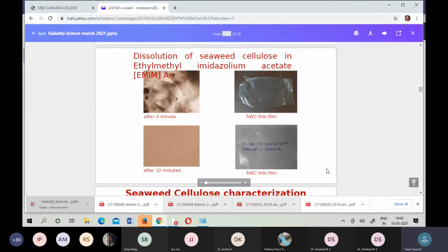It's fine. So, like I said, we use ionic liquid to dissolve the cellulose because cellulose solubility is very, very minimal in other solvents. In the first picture, you see the moment when you add cellulose inside the ionic liquid, that is ethyl methyl imidazolium ionic liquid. Even at the 0 minute, the reaction speed is quite high, and you can see some kind of disturbance happening, but within 10 minutes we can see the clear solution of cellulose.